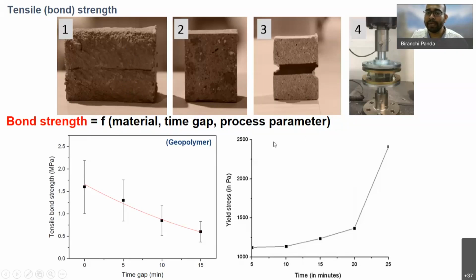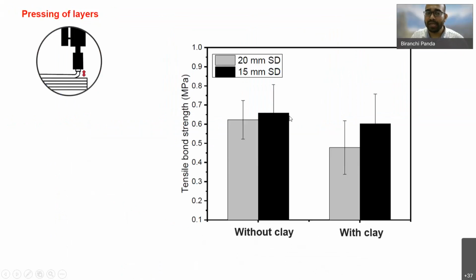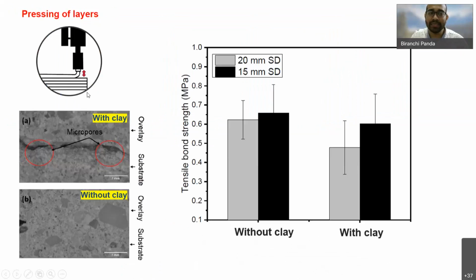What about process parameter? We have found that during printing, if you are printing with a very slumpy material and squeeze it, squeeze means you have to press the layer. In technical language, pressing a layer means that we decrease the layer height. When we decrease the layer height, and if the material is very fresh and slumpy in nature, meaning it has a very fluidic nature, then the porosity between the layers can be minimized.